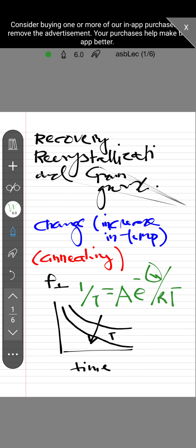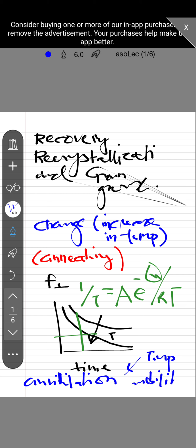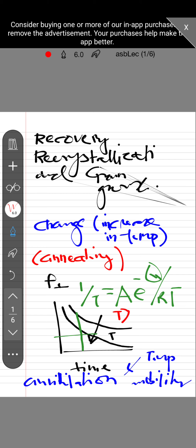Now the temperature at which the recovery process starts to take place, where there is an annihilation of dislocations, or the dislocations die out, is also known as annihilation. This annihilation is caused by the increase in temperature, which provides mobility to the dislocations. The temperature at which this process initiates is usually more than 1/3 of the melting temperature. So from this temperature onwards, the process of recovery takes place in the material.